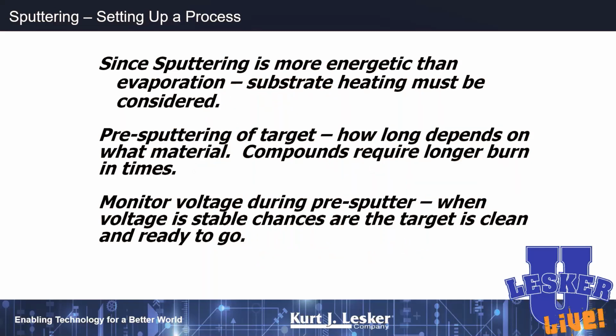Now, generally with sputtering, I recommend that you pre-sputter your targets first. If you pre-sputter them with the shutters closed in your system, you can sputter away the water that's built up on the surface of the target. I mean, the target should arrive to you from the manufacturer clean, pristine, ready to go. But as soon as you take it out of the package, you're going to have water and things like that deposit on it. If your technician's pretty clumsy and he's handled it with his hands, you're going to have fingerprints on it.